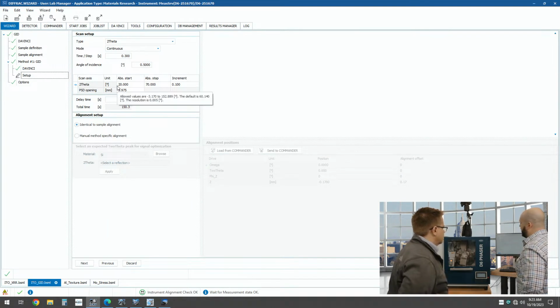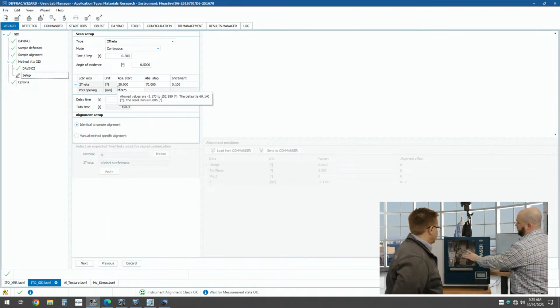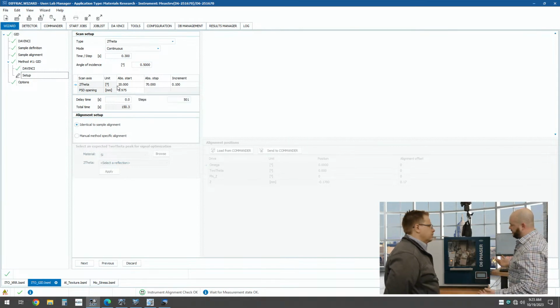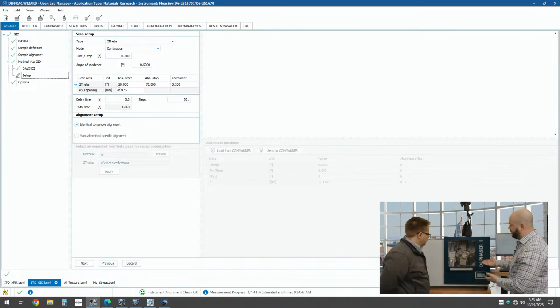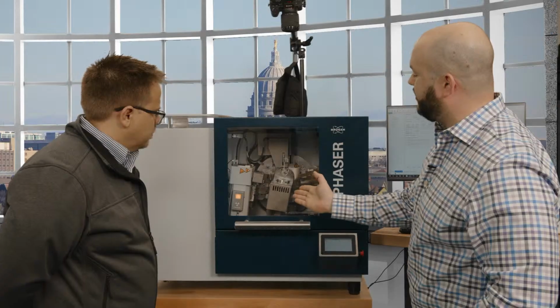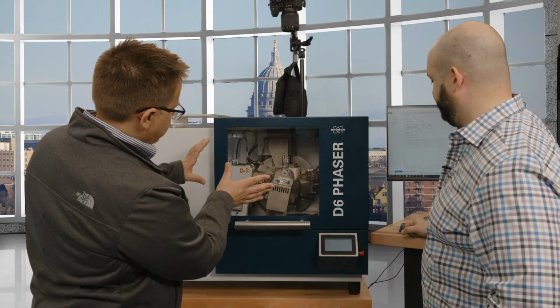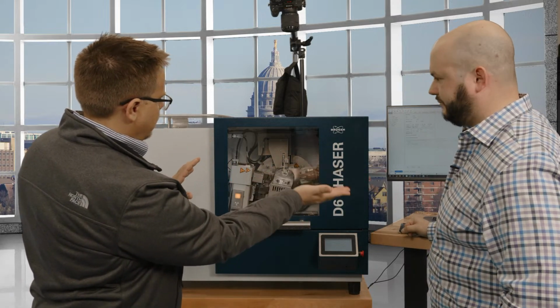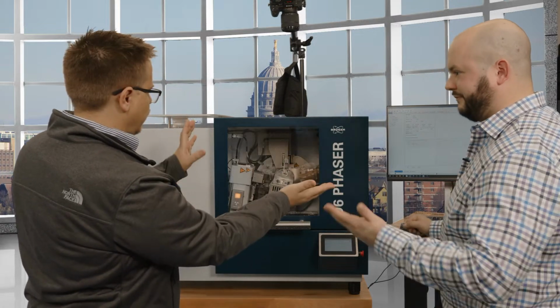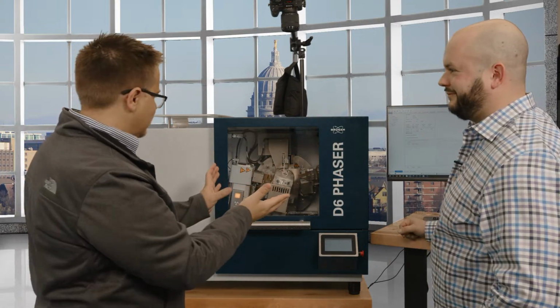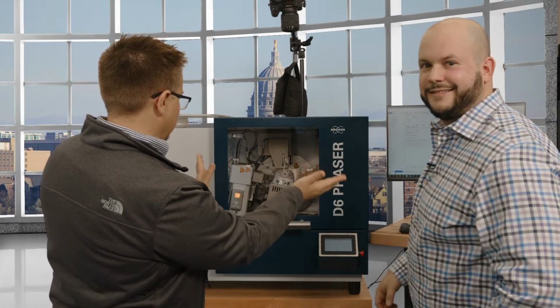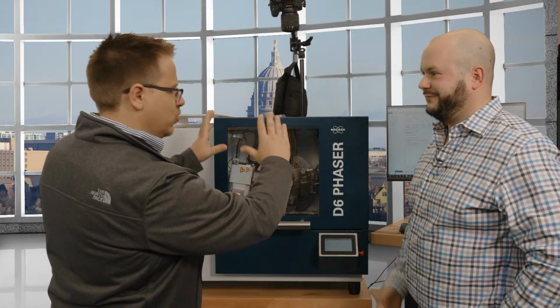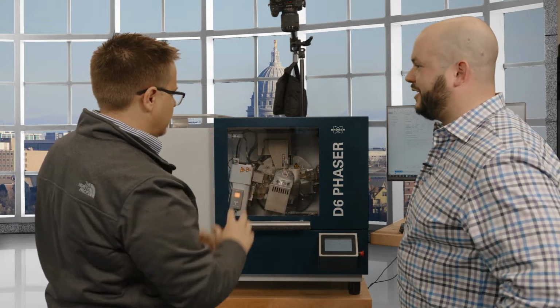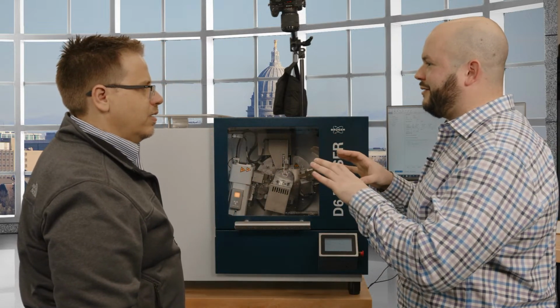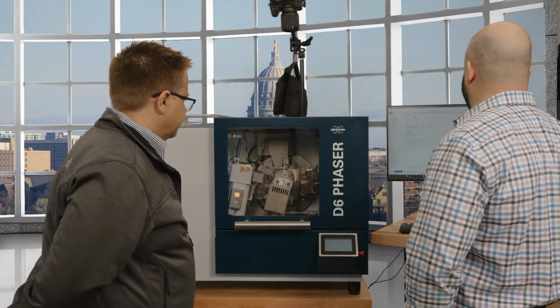You can see it's a 2 theta scan, effectively a detector sweep, because we're just keeping the incident angle fixed. Okay. And you can see right now, if we go to the instrument for a second, that there's an omega offset applied to keep that incident angle fixed. So that sample is all tilted. And it's slowly moving. It is kind of a complex measurement in this machine because the arms go up and the sample goes down. That's the fundamental motion, but then it also is tilting the sample. Yeah, so it has to keep those precisely coupled together to keep that incident angle fixed. So it's pretty cool engineering.